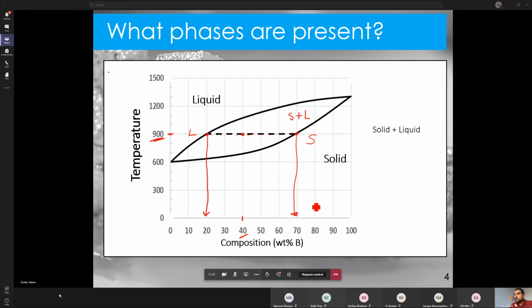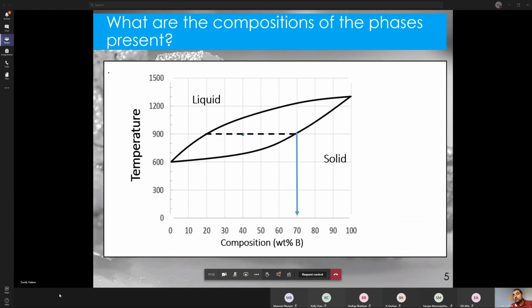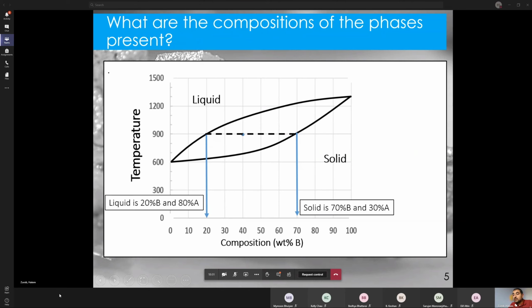So the point we have to realize here is we have two phases, solid and liquid. Each one of those phases has a different composition. It has a different makeup. The solid is 70% B. The liquid, on the other hand, is 20% B. Now, very often people ask, should these two compositions add up to 100%? So, for example, 20% B here and 70% B here, should they add up to 100%? The answer is no, because the composition of the liquid is the liquid's business. The composition of the solid is the solid's composition. They have nothing to do with each other. The only thing you have to check for consistency is, if you have 20% B in the liquid, it means there is 80% A. You have 70% B in the solid, that means you have 30% A in the solid. But the B in the solid and the B in the liquid are not related. They need not add to 100%.